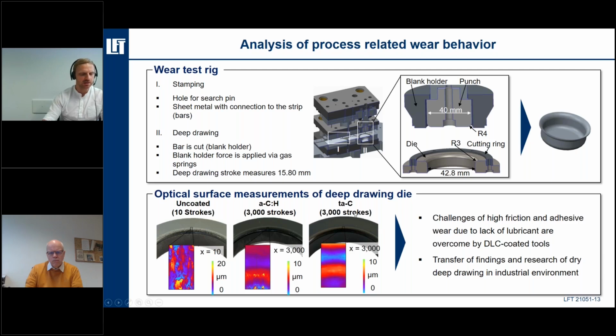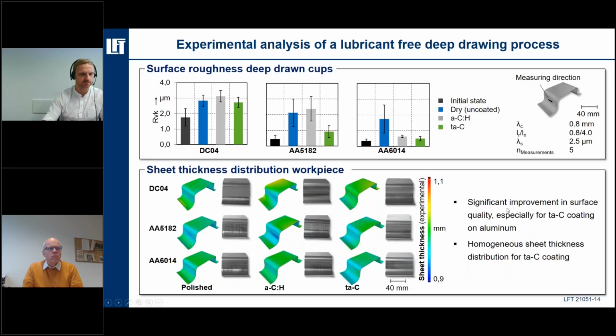With the ta-C coated tools, there are no visible wear signs after 3,000 forming operations with the aluminum alloy AA5182. So in this regard, the flat strip drawing test could be confirmed. The coatings reduce friction and wear, which in turn leads to an improved forming behavior of the forming tools. So further experiments have been performed with the DC04 and AA6014. With all materials, a failure-free forming was possible.